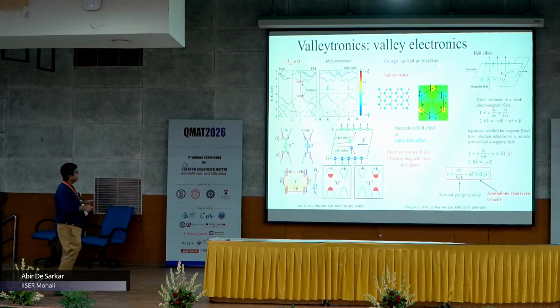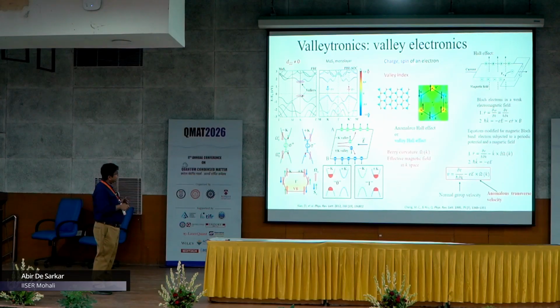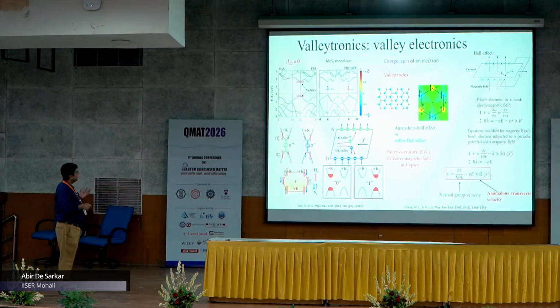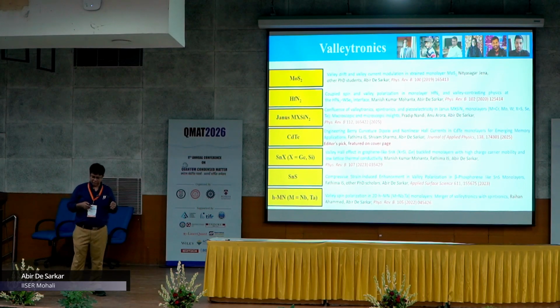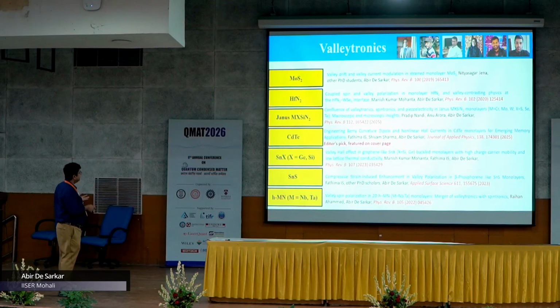So, apart from the charge and the spin degrees of freedom of an electron, another degree of freedom, namely the Valley degree of freedom, arises in a single layer MoS2, and this is the emergence of Valleytronics in two-dimensional monolayers. This single layer MoS2 happens to be the most widely studied 2D Valleytronic material. So, we have also contributed a bit in this direction, and we have also proposed two-dimensional monolayers beyond single layer MoS2, which show properties complementary to that of single layer MoS2. Like here in HfN2, it shows a large Zeeman type Valley spin splitting at the conduction band, not at the valence band.